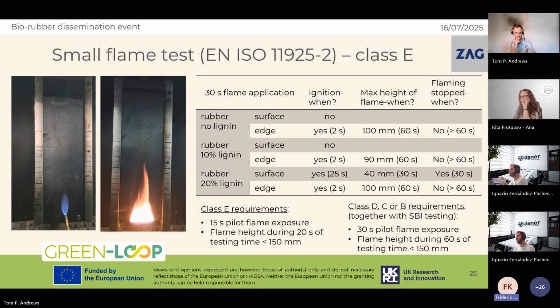The results that we have obtained on these materials are showing that actually the small flame test result is fairly good. It's complying to Class D, C, or B, not only Class E, which, to give you a comparison, is better than expanded polystyrene or extruded polystyrene or some other foam material that is typically used for insulation materials or being used on the facade as well. Next slide, please.